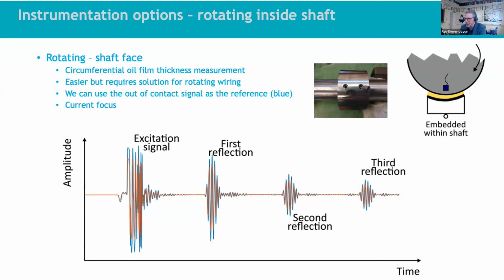And that has the advantage. Well, first of all, the signals are cleaner because you don't have all those interlayers to worry about. And secondly, you've got a continual reference. So we can measure out here as the sensor is here when there's no oil film, and we can pass into the oil film and back out again. So we can get a full 2D sweep of the oil film thickness as it passes around the circumference. So our signals, as you can see here, are much cleaner. And this is the current focus.